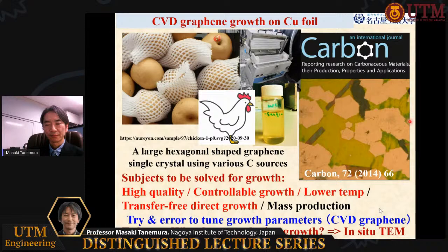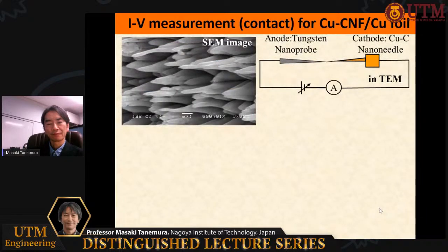Besides this, we want to know what happens during graphene growth. For this purpose, in situ transmission electron microscopy is very powerful, and carbon nanofiber is very suitable for this purpose. This is a case of copper-included carbon nanofiber. You know, copper is known as a typical catalyst for graphene growth in CVD. So the transformation from amorphous carbon to graphene will be expected. This is a SEM image. Relatively thick carbon nanofibers grow, and we put this sample in the TEM system and apply the voltage.